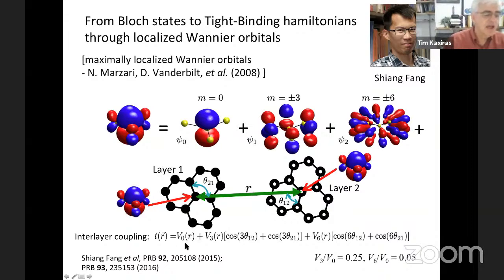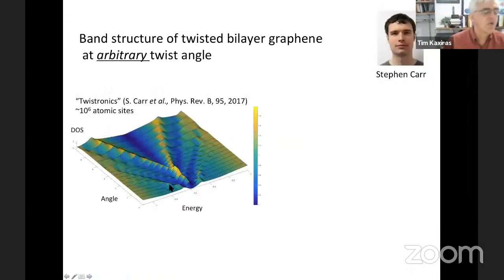And then you can construct an interlayer interaction, this hopping matrix element between layers that includes all these terms: the V0 term, which comes from these interactions, the V3 term that comes from the next angular momentum contribution, the V6 term that comes from the next angular momentum, and so on. And these are not negligible. This term is about 25% of the strength of this, and this is about 5% of the strength of the first term. So they're not negligible. But this gives us the ability to do very accurate calculations, and that's how we were able to produce this picture for very large systems, including of order 1 million atomic sites.